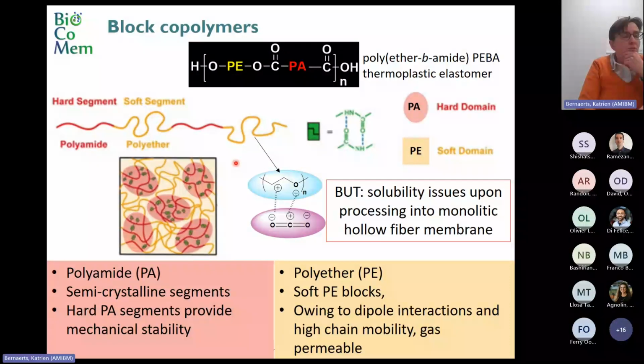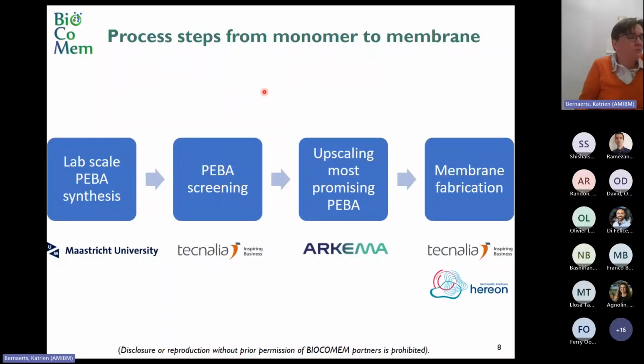Now, the issue with commercially available PEBAs is that in order to make, for example, monolithic hollow fiber membranes, you need to use a solubilization process, and those polymers are hardly soluble. So we will propose a strategy to tackle this issue. First, I will give you an overview of the process steps from monomer to membrane. So from the monomers, we make PEBA at lab scale. That's a task done by us, Maastricht University. Then those PEBAs are screened for membrane performance by Tecnalia, and the best polymers based on the screening results and based on the processability are upscaled, and this upscaling is done by Arkema, and those upscaled polymers are then used for real membrane fabrication by Tecnalia and hereon.